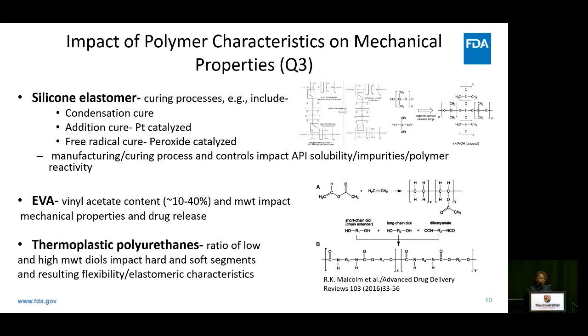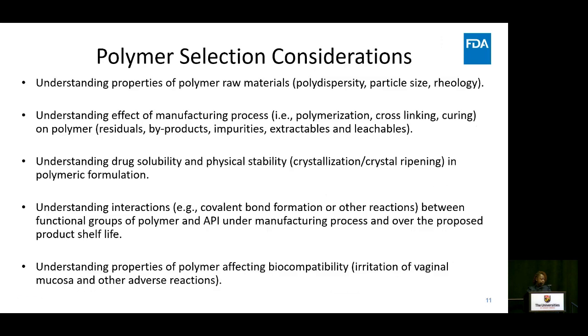When it comes to the EVA polymer, it's worth noting, as we noted from yesterday's talks, that the vinyl acetate content and the molecular weight significantly impact the mechanical properties of the final vaginal systems, as well as the drug release. Hence, we keep on stressing certain factors that applicants should consider when selecting their polymers for use. The first is we recommend that applicants demonstrate strong understanding of the properties of the polymer raw materials when it comes to the polydispersity, particle size, and rheology.